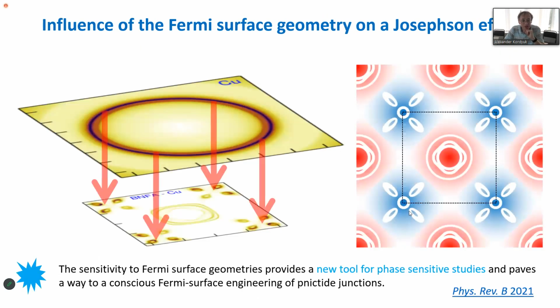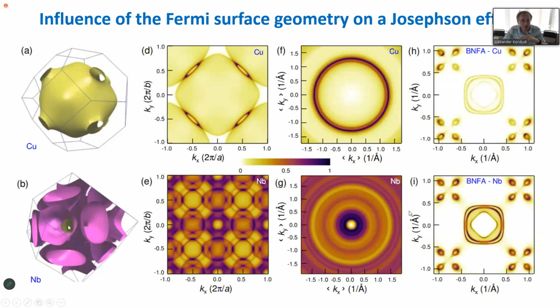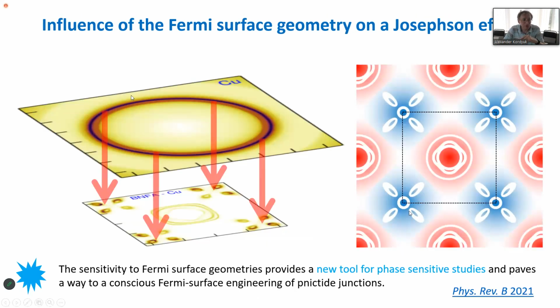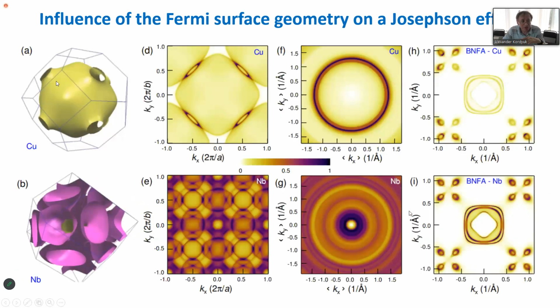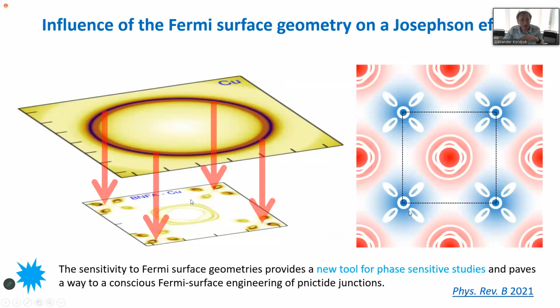Here we have, let's say, above we have niobium, and in between you see the Fermi surface of niobium, it is very complicated. Therefore, the projection of the Fermi surface will be almost constant. But the projection of the Fermi surface of copper is very simple. It will be like a ring. And the Fermi surface of single crystalline iron-based superconductors is very defined, right?